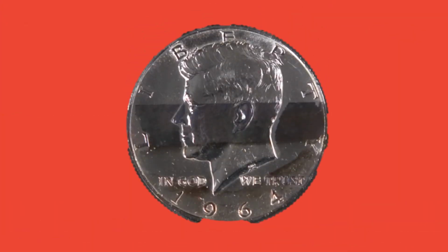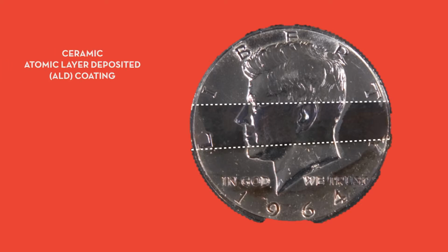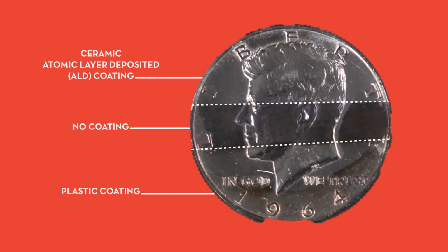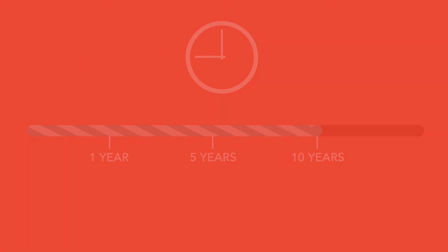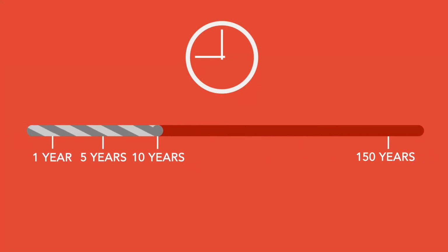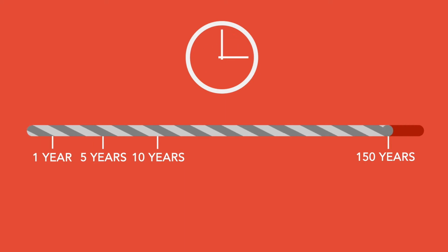I found that the ceramic ALD films lasted 15 times longer than the plastic coatings. That's a huge improvement. For art conservators, this means that instead of every 10 years, they could wait 150 years before having to polish and reapply a coating. Additionally, I found a way to completely remove the ceramic coating without damaging or significantly changing the silver object. This is a critical step if we ever want to use these films on real art objects.